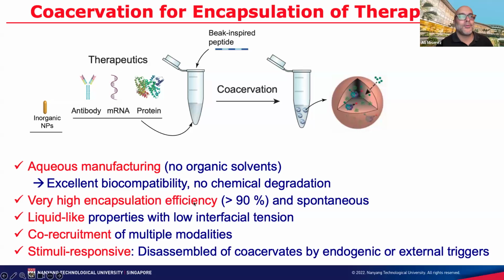You have very high encapsulation efficiency, over 90%. The droplets are still liquid-like, okay? And then you can also recruit different modality, and most importantly, you can make them stimuli responsive. So what I mean here is that you can disassemble those coacervates either endogenously by encoding something inside the peptide, or by external trigger, for instance, a magnetic field or near-infrared, if you encapsulate other kind of inorganic nanoparticle inside the droplet.